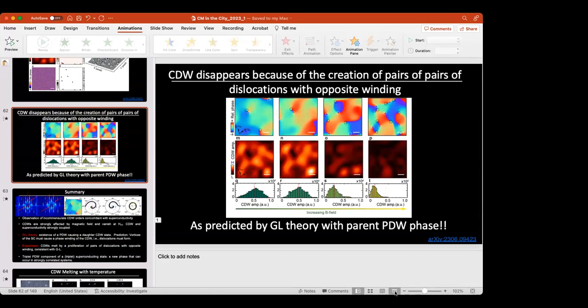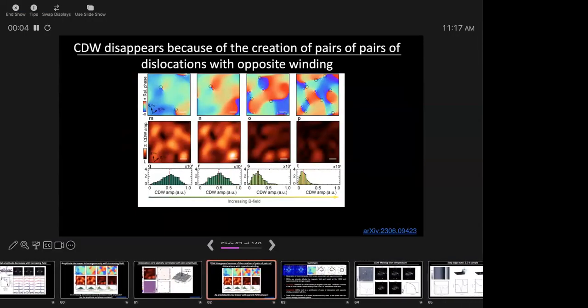I can't find it, but let me just say that in this field of view, if you put all the dislocations from all three directions on top of each other, this is just one direction, you get, for example at 8 Tesla, about 3 bunches. And those 3 bunches are how many vortices you expect in this field. This is probably 8, this is probably 5. This length scale is probably 400 angstroms.